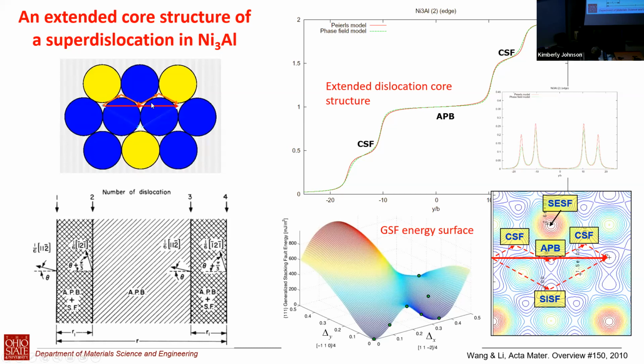And this is the original. If you have just a disordered FCC phase, that's the translation vector. Now, because of the different chemical species, because of the ordered structure, the translation vector doubles. So this is a half <110>. Now you need a full <110> to have a complete repeat of the crystal structure.